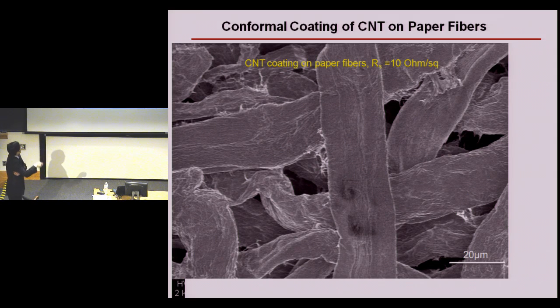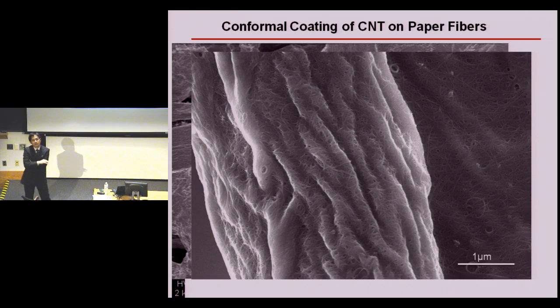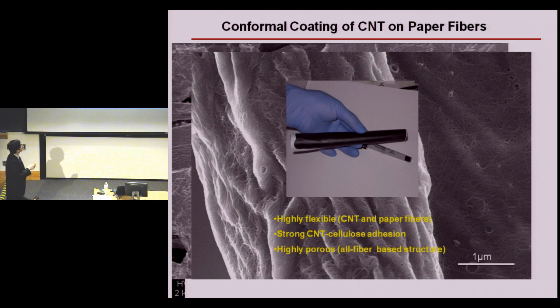This is the structure of paper fibers with carbon nanotube coating on the surface. If you zoom in, you will see the nanotubes are conformally coated on the surface of the paper. Because nanotubes are a one-dimensional material, they can overcoat the paper surface so well that they can link all these paper fibers together. And that's why this whole paper turns into a highly conductive medium.